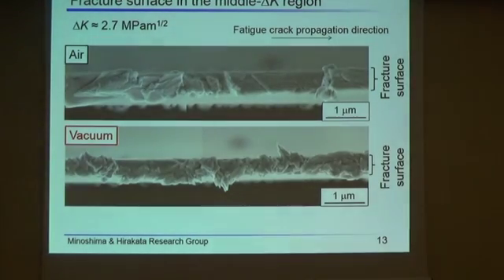So to investigate the vacuum effects, fracture surface observations were conducted, as shown in this slide. This is a fracture surface in the middle delta K region in air and vacuum at the same delta K. On the fracture surface fatigued in air, relatively flat surfaces with sharp edges were widely observed. In contrast, on the fracture surface fatigued in vacuum, flat surfaces are rarely observed, and instead, blunt surfaces with fine roughness are widely observed.